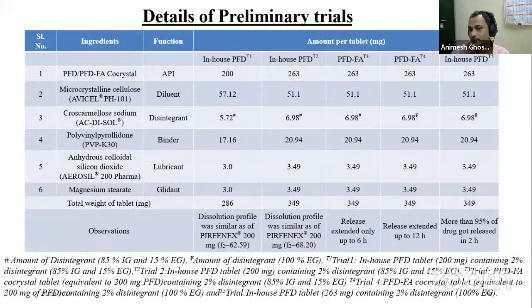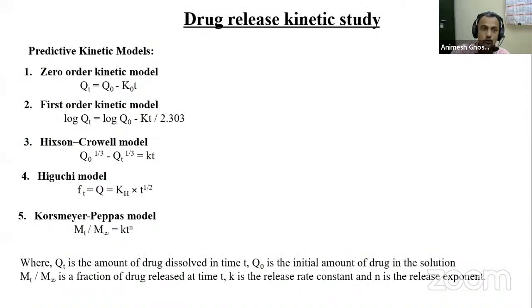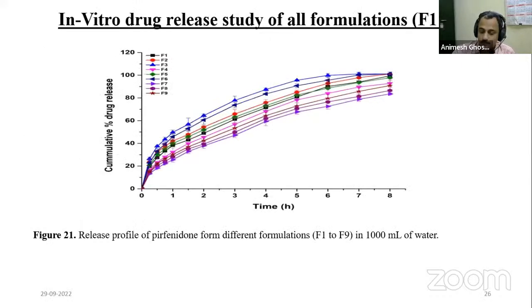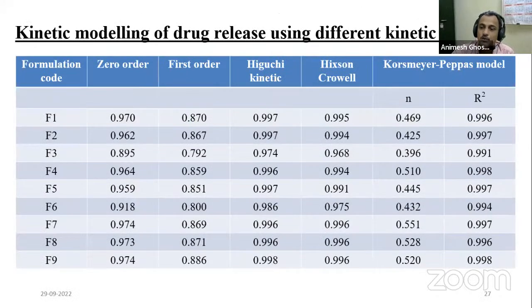First, we tried to prepare 200 mg tablets by taking the equivalent amount of co-crystal, and then we prepared 263 mg tablets by incorporating the equivalent amount of the co-crystal. So these are, as all of you know, the predictive kinetic models. We have done the dissolution study. From the Korsmeyer-Peppas model, it was observed that in most cases the dissolution mechanism is basically Fickian diffusion, that means Fick's law of diffusion.